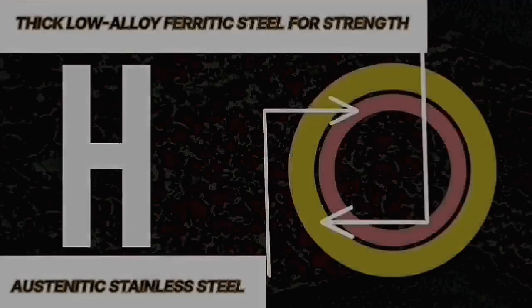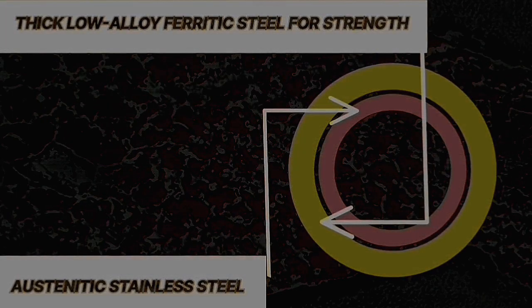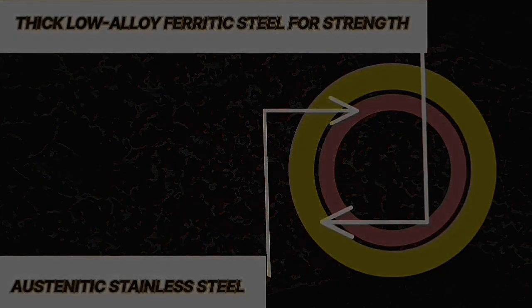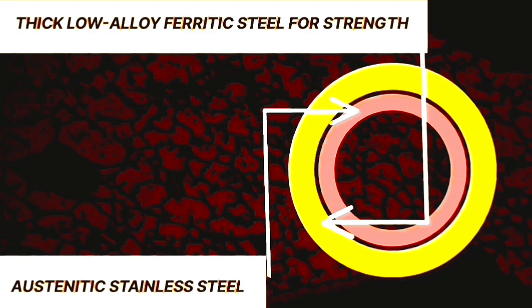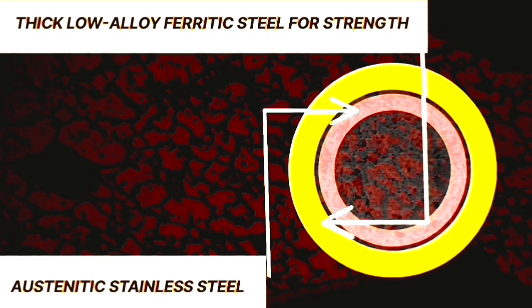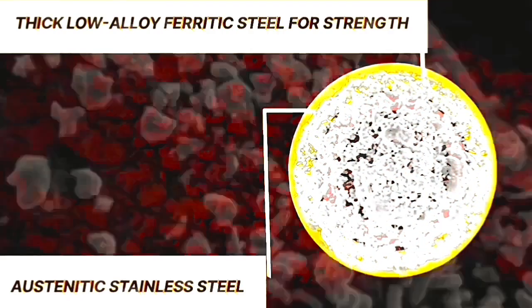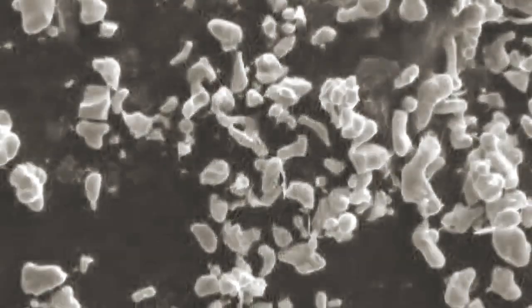But to get back to hydrogen. The chromium-molybdenum steels used for many high-pressure hydrogen vessels contain significantly less chromium, typically in the range of 1 to 9%. At these concentrations, the chromium is not primarily added to provide corrosion resistance. Instead, it improves the steel's high-temperature strength and promotes the formation of stable carbides that help resist hydrogen attack and embrittlement. It also quantum tunnels, though there's really no hope in trying to contain the smallest, lightest element.